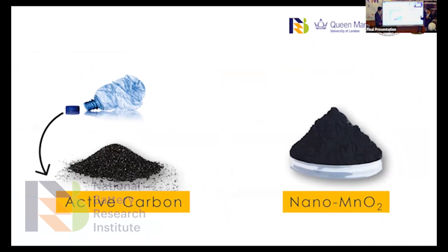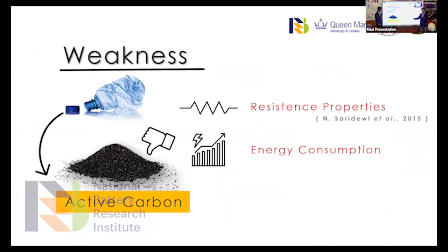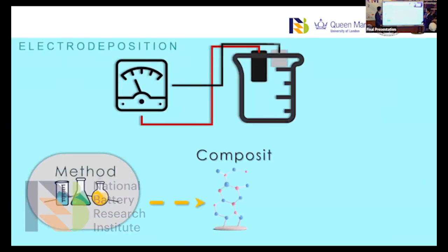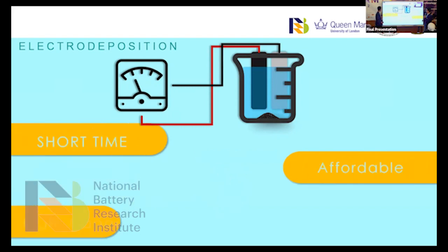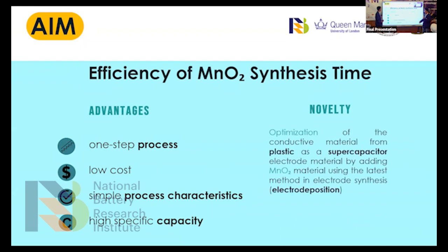But activated carbon needs added manganese dioxide for optimization, because activated carbon has weaknesses like resistance properties and high energy consumption. For the composite, we use the electrodeposition method, which is a simple fabrication with a short time to produce precipitate and affordable high capacity. To control the amount of precipitate, we need voltage or concentration of solvent. Our aim is efficiency of manganese dioxide synthesis time, with advantages like a one-step process, low cost, simple process, and high capacity.